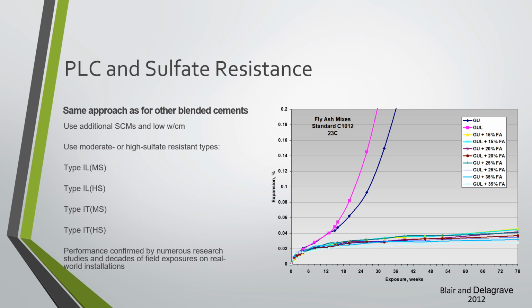With the same air content in all of them? Yes, all this testing that you're seeing here was the 1293 testing that they were doing. And then the C1012 testing, which now we're looking at, is all sulfate resistance. So these are mortar bar testing. So 1293 is a concrete prism. The 1260s, which is another ASR test, those are mortar bar prisms.